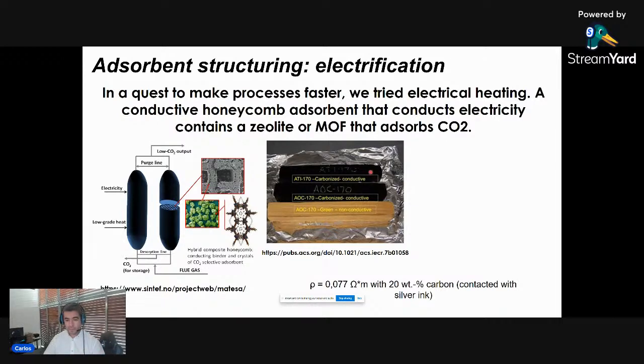So here you see 2 materials. There's one paper from the group of Paul Webley that I also co-authored. It has been done with this material. We kept the other one. So there are 2 different compositions where the amount of activated carbon in the sample changes, I think, by 1.5%, but the electrical conductivity changed by one order of magnitude. Actually, it changed 25 times.